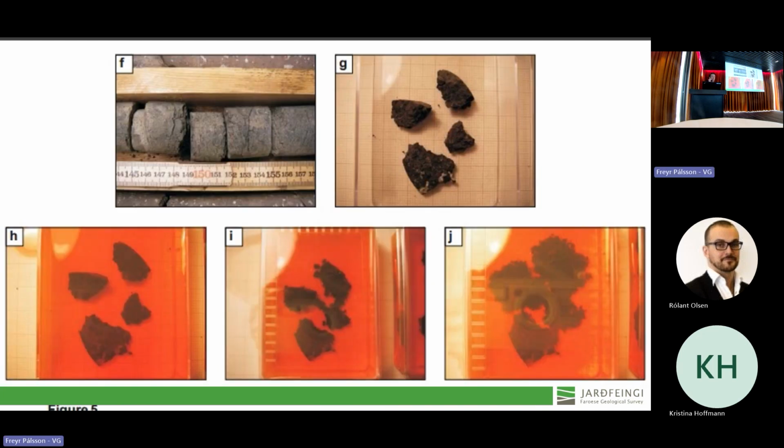But a more rigorous way to do it is to change water out with ethylene glycol. This was introduced by the U.S. Army Corps in 1949 when they tried to test the durability of aggregates for pavements and concrete.